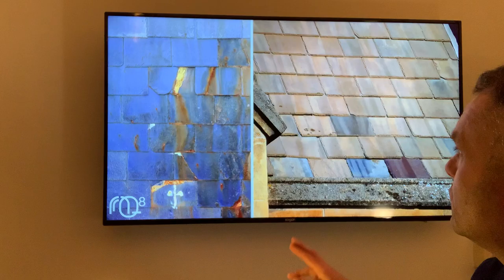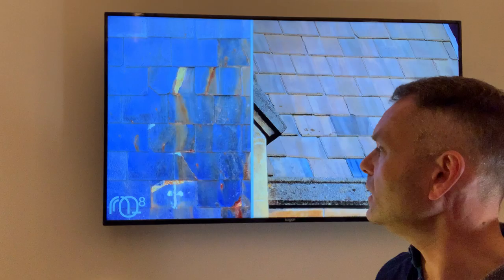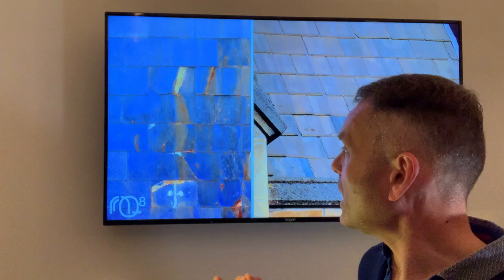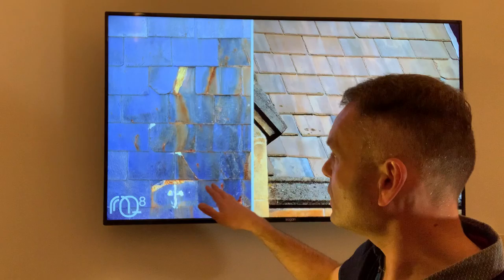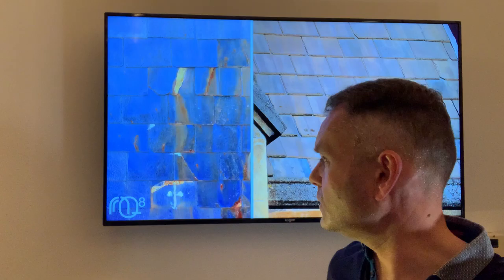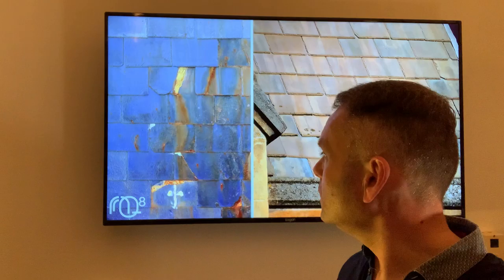The image on the left shows a poor quality Spanish slate put onto a building in Gawler in the 1970s. This slate contains a lot of iron pyrites, which basically rust — iron is embedded within the slate itself, causing weak points throughout. You can see the slates are deteriorating quite rapidly; some have fallen out, and there are attempts at temporary repair using silicone.